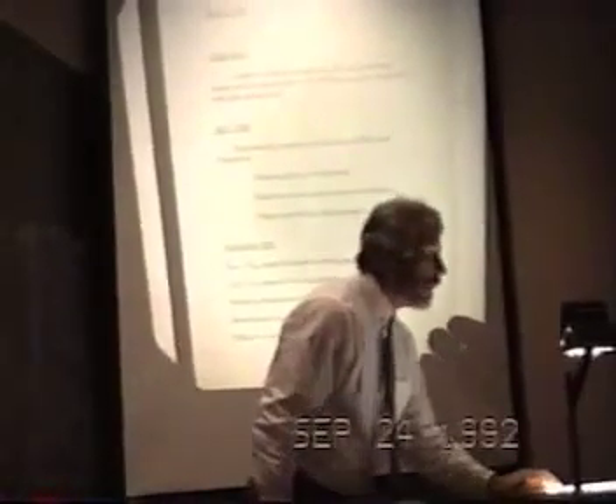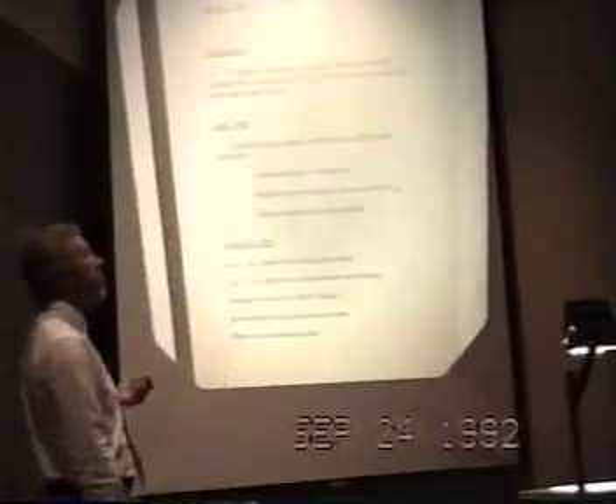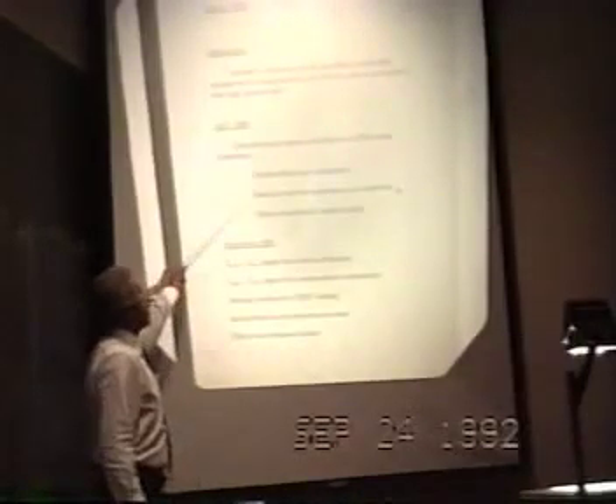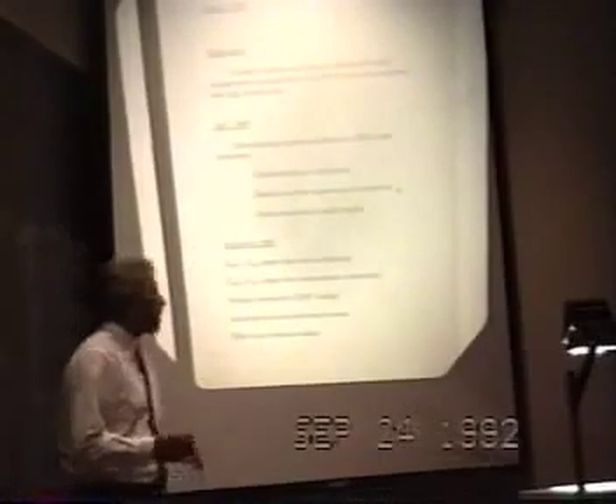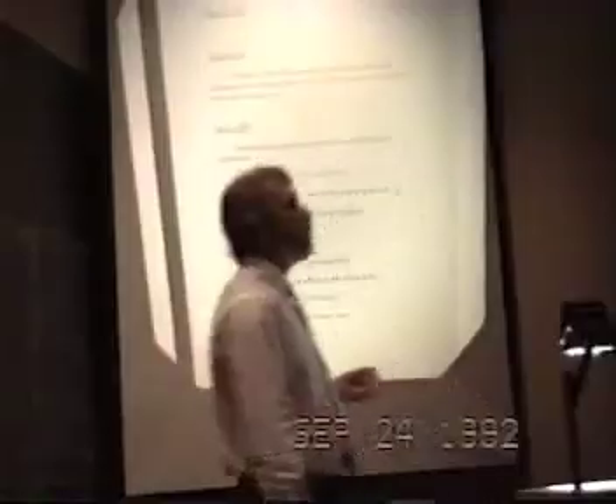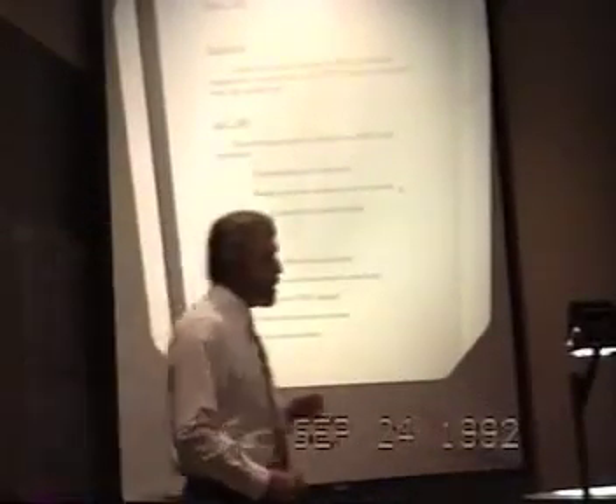That is, we used our experience in creating high loadings and monitoring the loading of the deuterium-palladium system using resistance ratio and AC impedance methods in order to establish this experimental program. And the idea was that we would obtain scientifically useful results, whether or not replication was successful. What we know today, and what I hope to lead you towards the end of the lecture, is